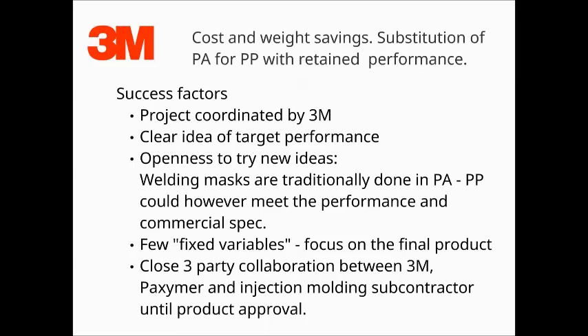The actual end of this was that they typically make their welding masks, which is what this was, from polyamide, and we enabled them to make it from polypropylene and still retain product performance, or meet the spec that they had set up. So they were looking for a low-cost solution. Of course that also reflected the spec of the product, but nonetheless it's a strict requirement, and they had very high requirements in surface and on dropping tests and shooting tests and so forth. So it's a challenge to meet these mechanical requirements.